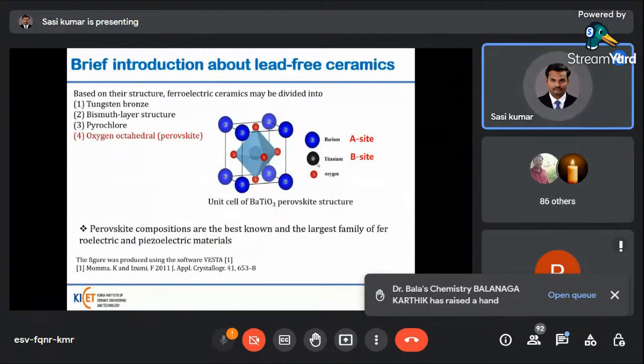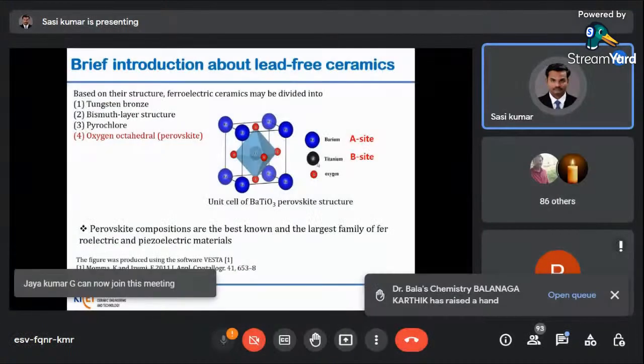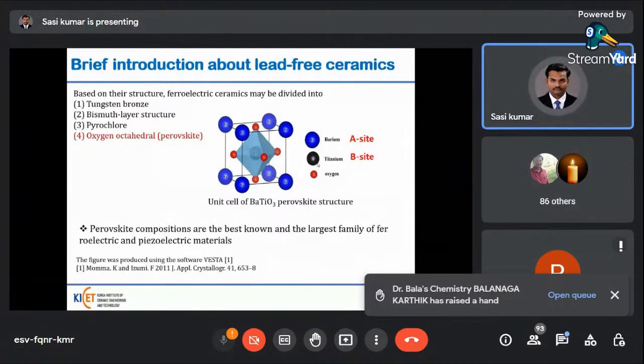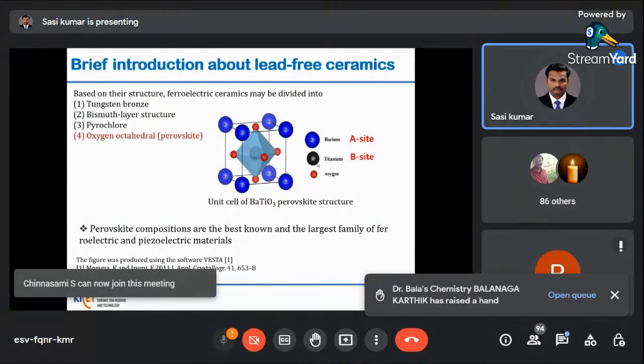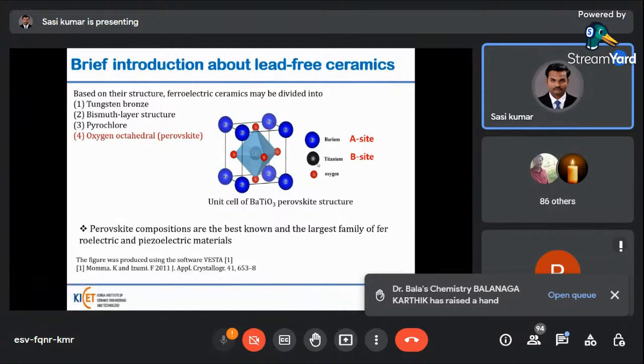Then, a brief introduction about lead-free ceramics. Okay, here is the BaTiO3 perovskite structure. Barium is the A site, titanium is the B site, and oxygen is at the corners. There are different structures: tungsten bronze, bismuth layer structure, pyrochlore, oxygen octahedron. That is the perovskite structure. The perovskite structure is a well-known material.